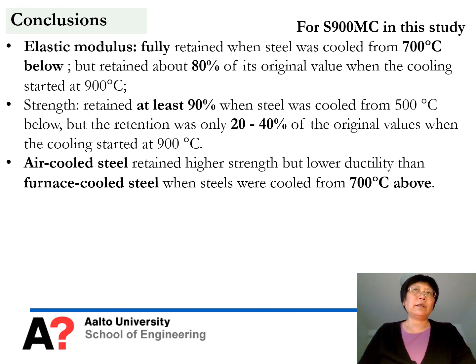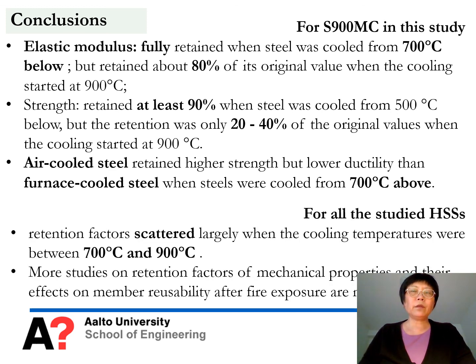And for the studied steel, the air-cooled steel retained higher strength but lower ductility compared to the furnace-cooled steel from a 700 degree cooling temperature. And for all the studied high-strength steels, the scatter of the retention factor is between 700 degrees and 900 degrees. It seems that more study on the retention factor of mechanical properties and their effect on member reusability is necessary.